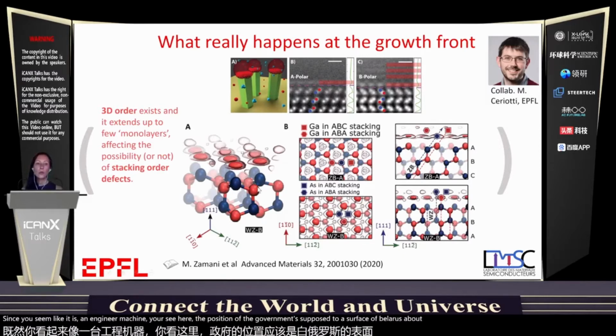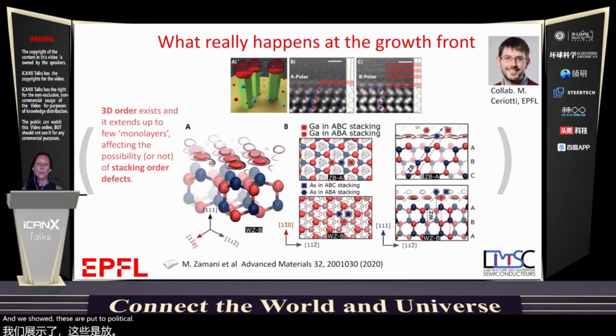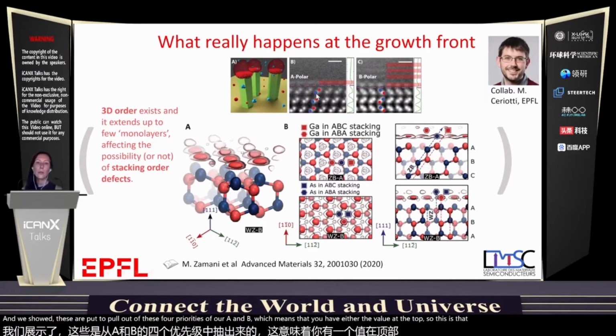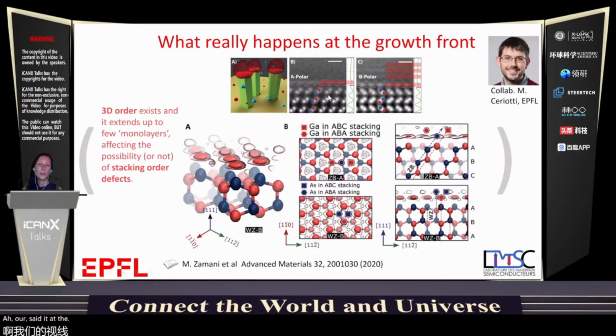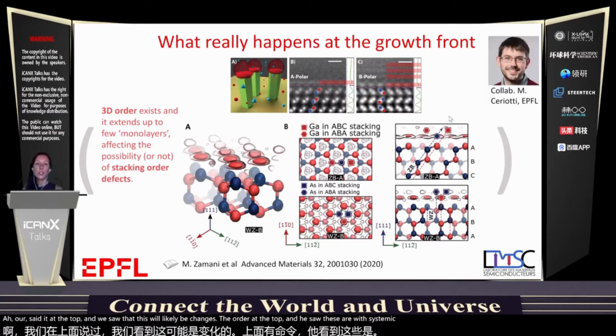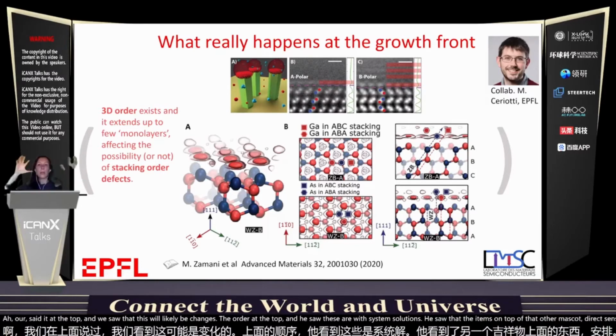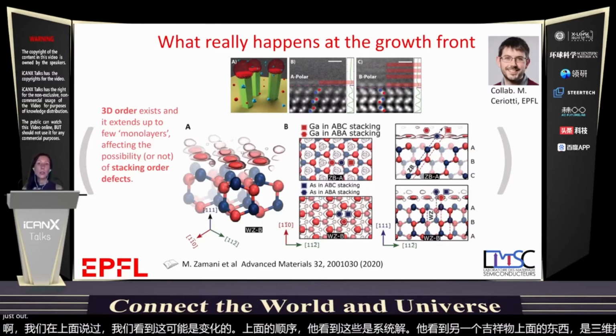And we showed this for two polarities, A and B, which means that you have either the gallium at the top, so this is the dimer of gallium arsenide, either you have gallium at the top or arsenic at the top. And we saw that this polarity really changes the order at the top, and he saw this with his simulations. He saw that the atoms on top of the gallium arsenide arrange themselves in 3 dimensions, nearly like a crystalline phase, but just gallium atoms and no arsenic.